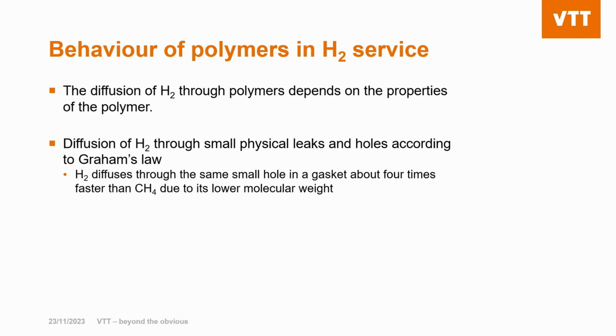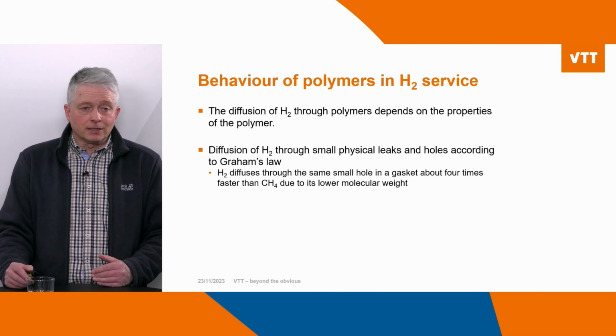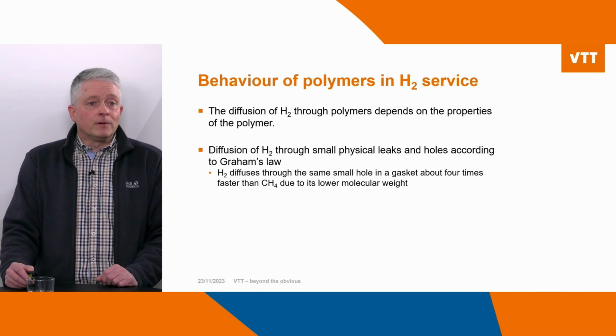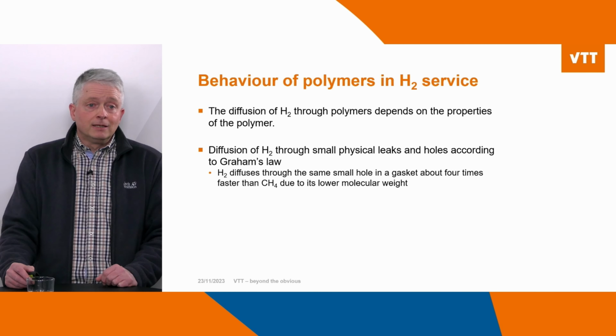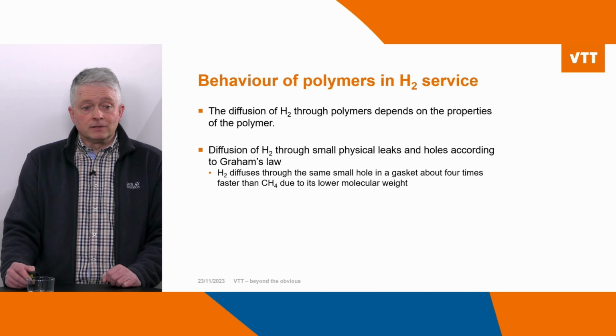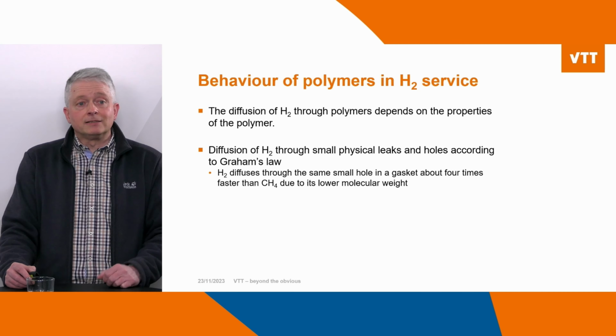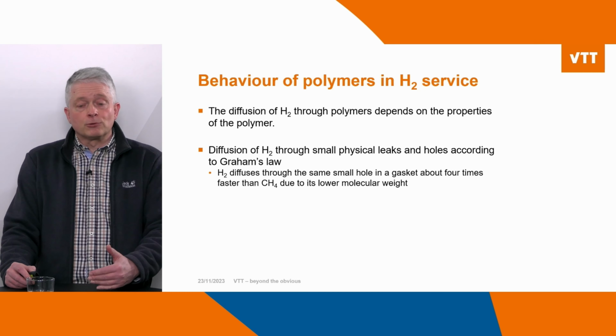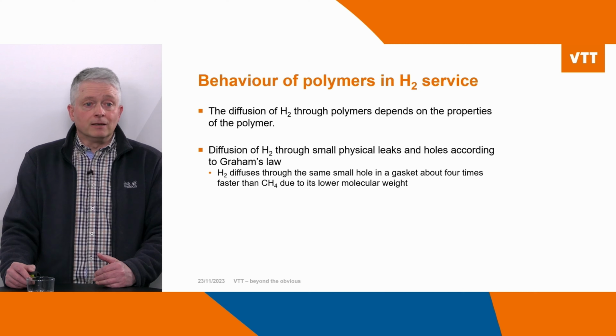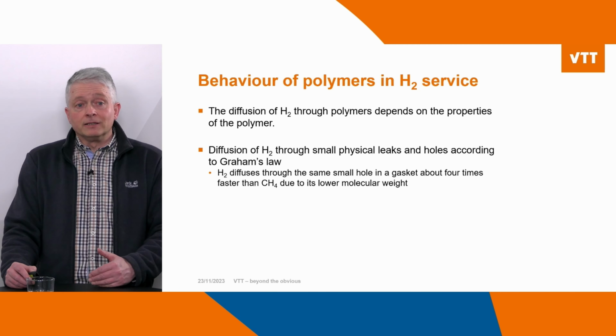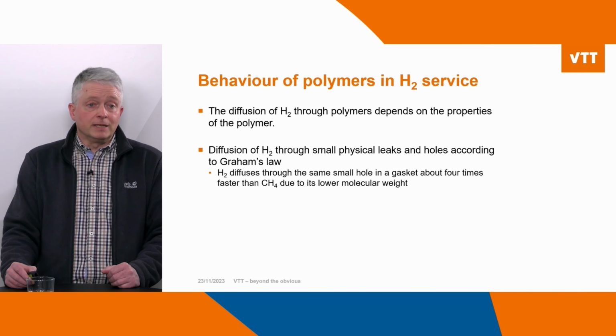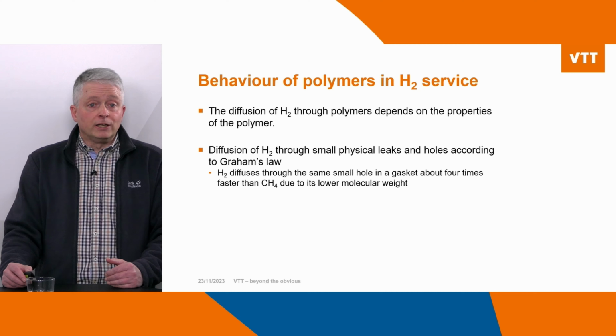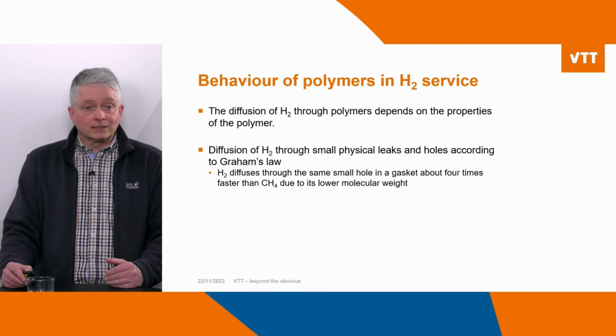The diffusion of hydrogen through polymers depends mainly on the properties of the polymer. It's not so much caused by the size of the atom or of the molecule, which is quite small. On the other hand, when there is, for instance, a very, very small physical leak in a seal, Graham's diffusion law comes into action, which says that the diffusion of gas through a very small hole depends on the molecular mass of the gas. And as hydrogen is a very small, very light molecule, the diffusion is quite fast. For instance, it's four times faster than that of methane. That needs to be considered when you construct or plan some seals or gaskets.